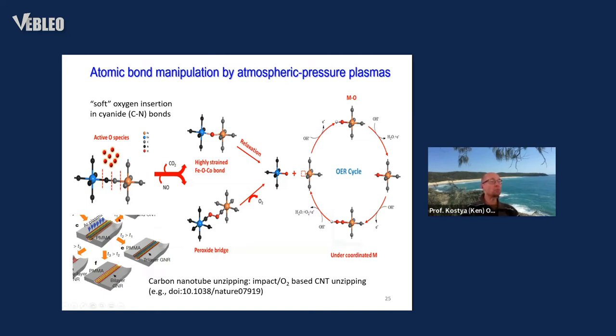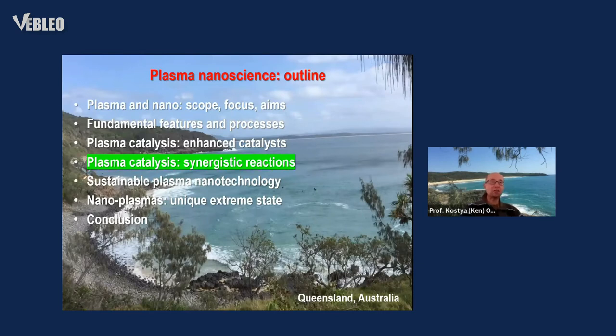The interaction of oxygen species with various nanoscale objects has also been reported by other authors, such as unzipping of carbon nanotubes, when oxygen plasma interacting with carbon nanotubes led to the formation of highly controllable graphene nanoribbons. This interaction is unique to the plasma and is effective only under very specific conditions that are found after rigorous plasma-specific research. Next is highlighting the synergy of interaction between the catalysts and the plasma when they are used together.